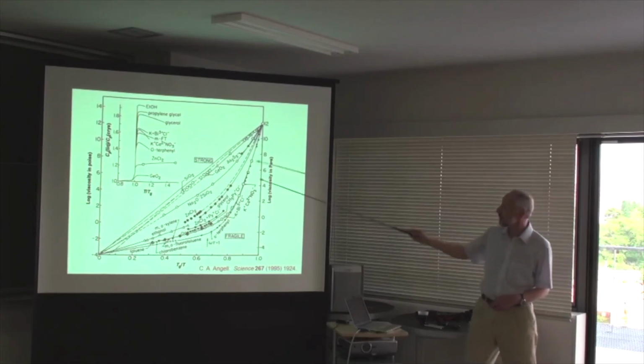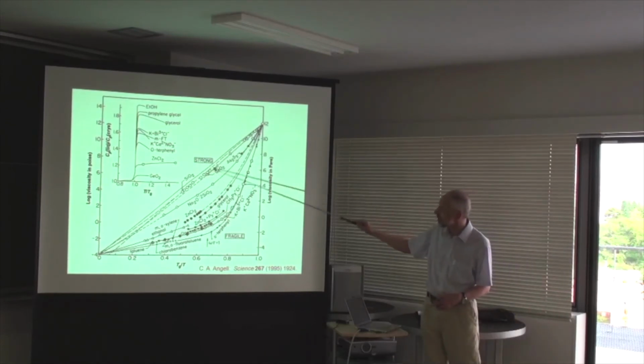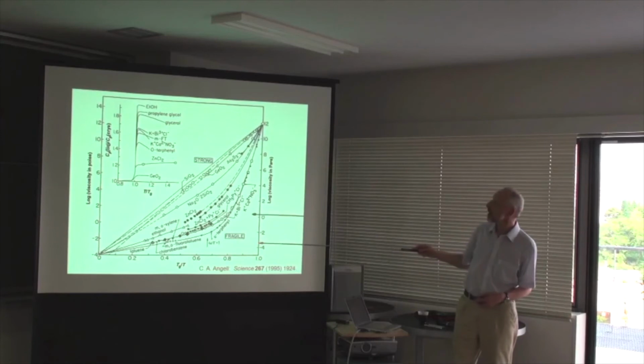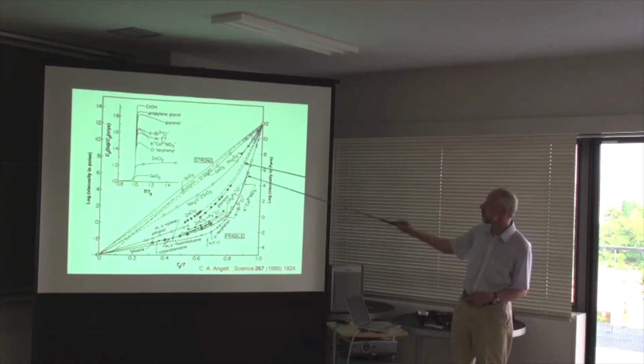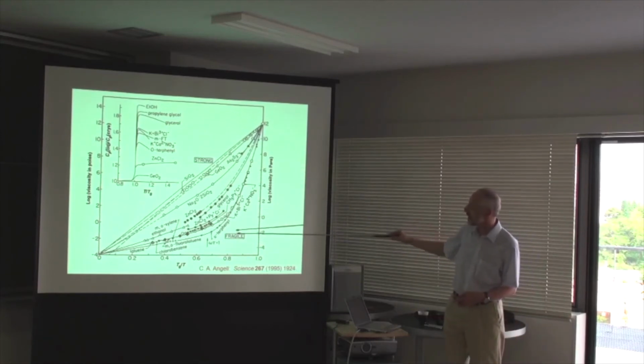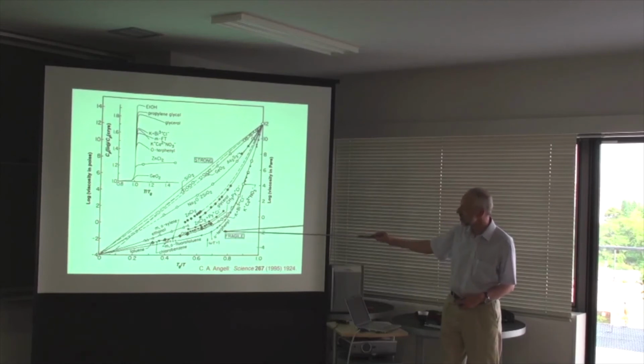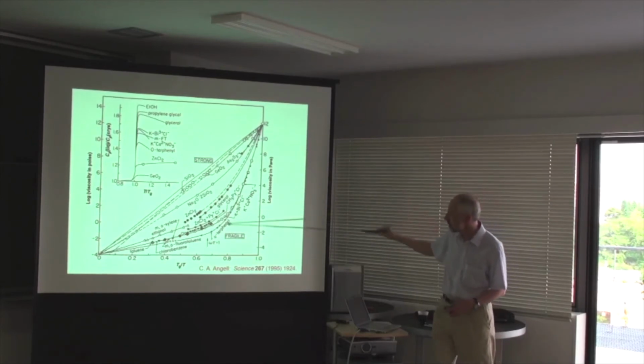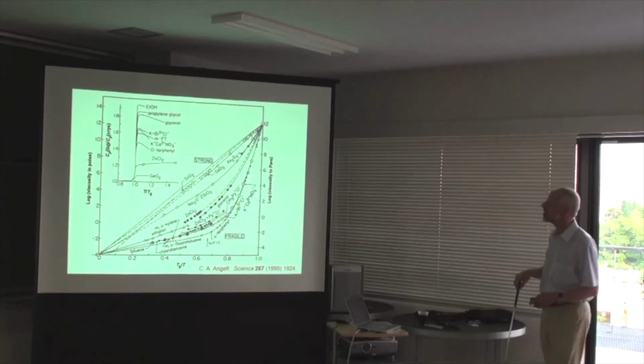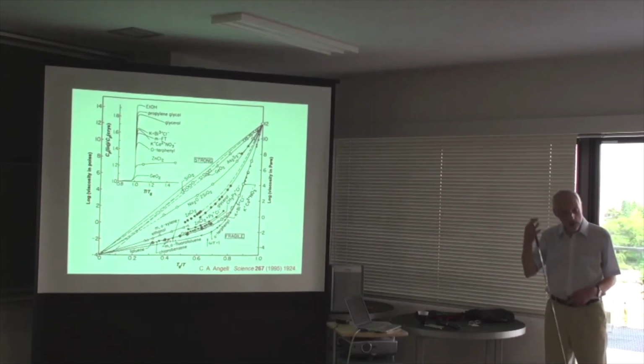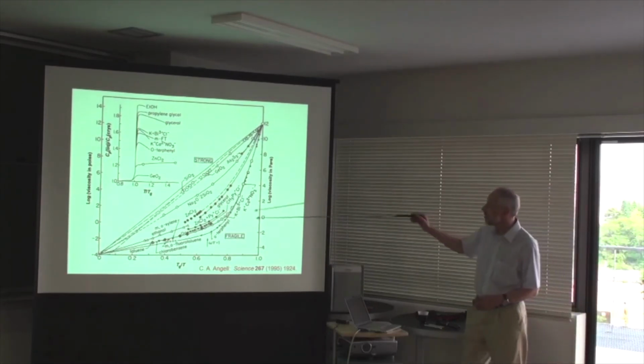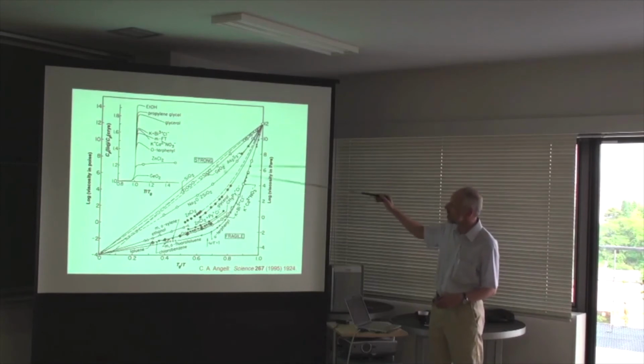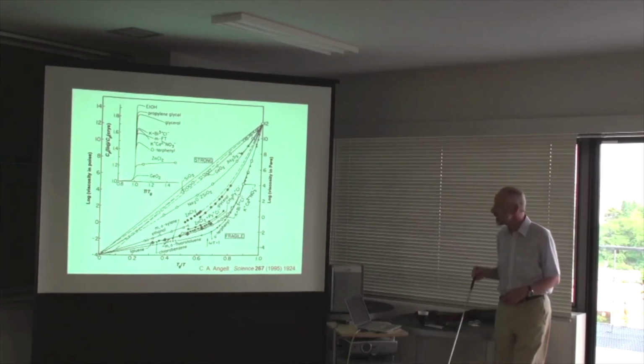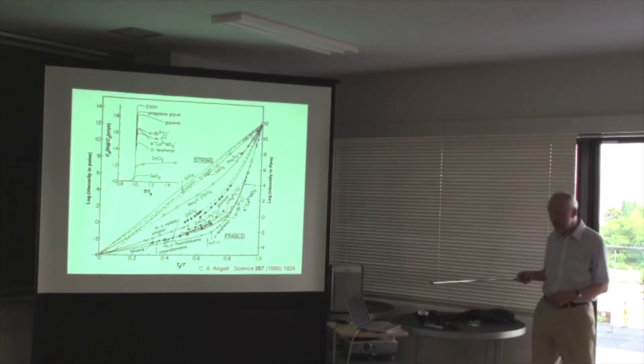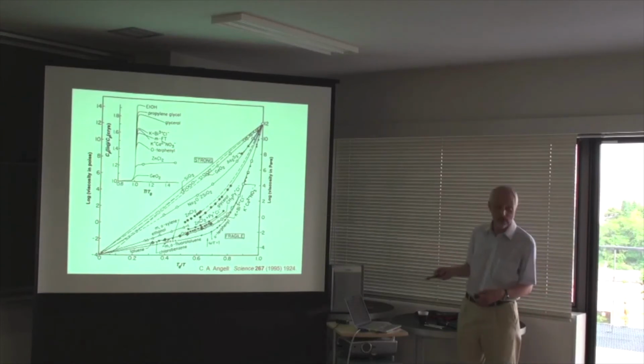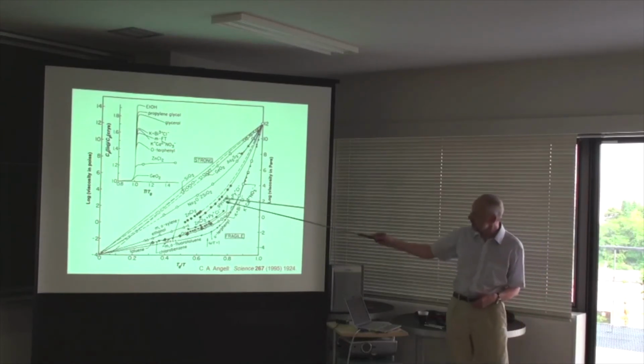But if it is something that forms a network, this is a rather straight line behavior, classic activation energy, Boltzmann law. If it's something like one of these organic liquids, terphenyl, it has a very curved line, not a simple activation energy. And people think that almost any glass forming system should have a viscosity that sits somewhere in this spectrum of behavior. The question might be, where do metallic glasses sit, and where do others sit as well? And the answer will turn out to be somewhere in the middle.